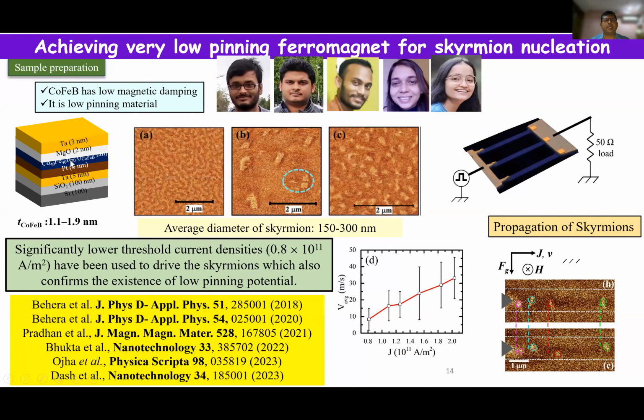These are all room temperature, and we found that we could achieve a very small pinning landscape in our cobalt iron boron film, which was published recently, and you can actually have a very low critical current density. To the best of our knowledge, this is probably the lowest in the literature, and we want to explore more. You can see some publications where we report our work on skyrmions.